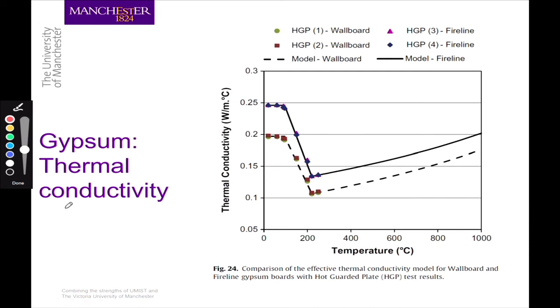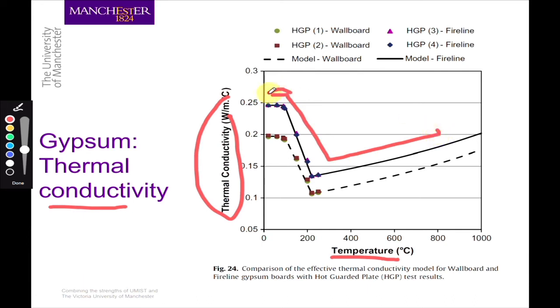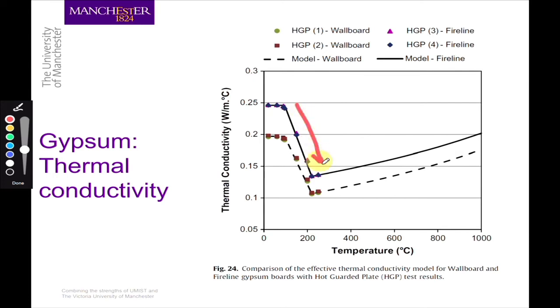The other aspect, of course, is thermal conductivity of the material. If we look at the thermal conductivity of gypsum as a function of temperature, we will find this relationship. It starts with an ambient value, and then decreases, and then increases. This decrease, which I think is quite well agreed, is because water is disappearing from gypsum. Water is more highly conductive than air inside. So if water is replaced by air, then the thermal conductivity decreases. And then afterwards, the thermal conductivity increases.